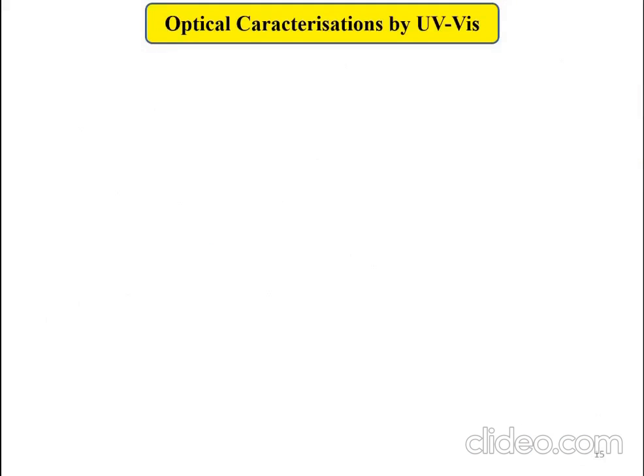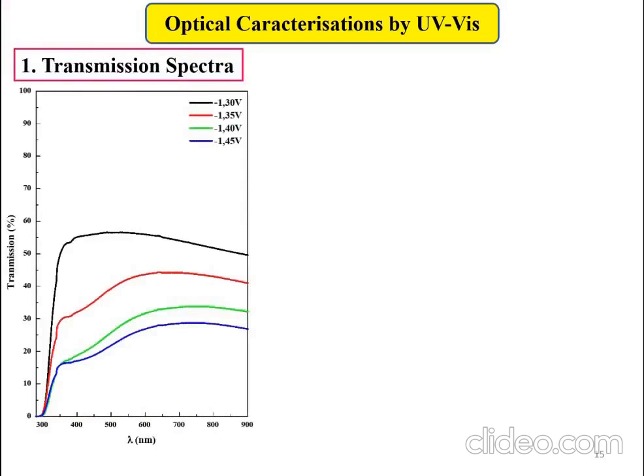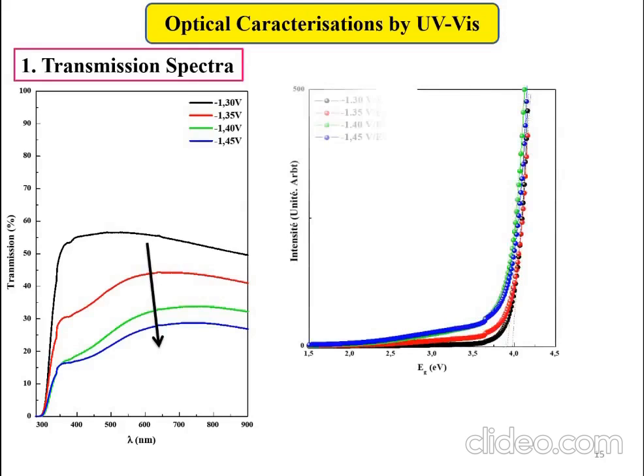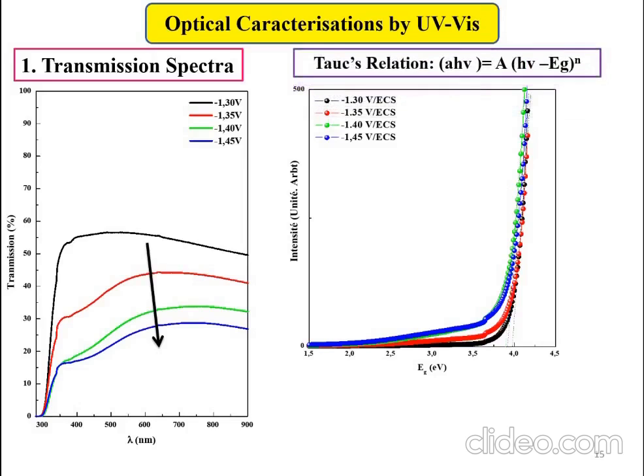The optical characterization by UV-visible was studied. The optical transmission of the nickel oxide deposit decreased from 55 to 25% in the visible range as the deposition potential increased from minus 1.30 to minus 1.45 volts respectively, with a shift of the absorption edge towards the blue.